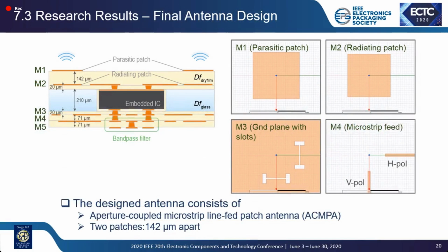So let me show you the final antenna design. We chose to have 142 microns for the separation between the parasitic and radiating patches. Those are both squares, but they have about a 200 micron difference in terms of size. And also we have a ground plane in M3 with dumbbell shaped slots, and those patches are fed by microstrip lines.